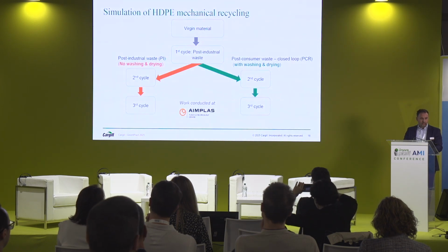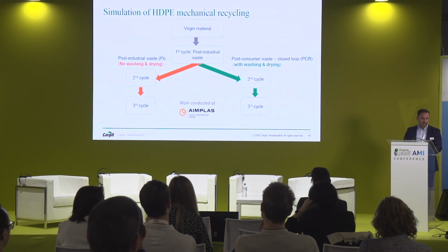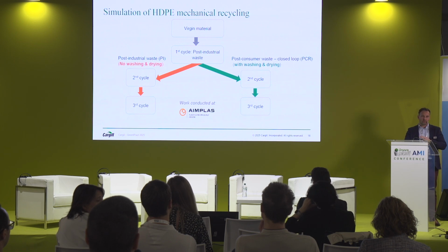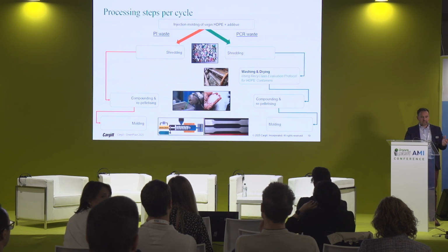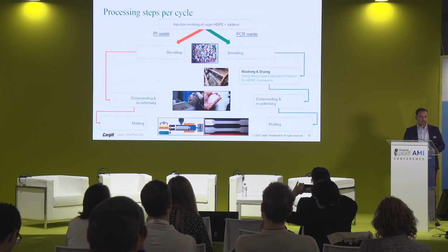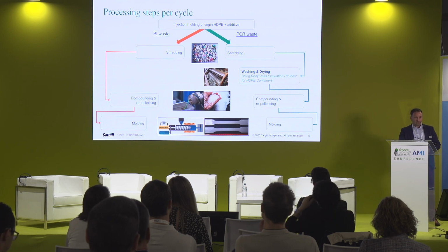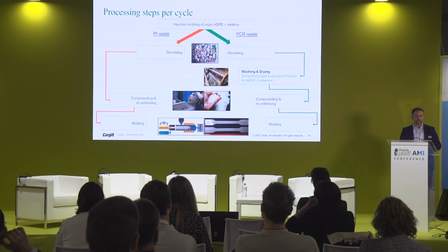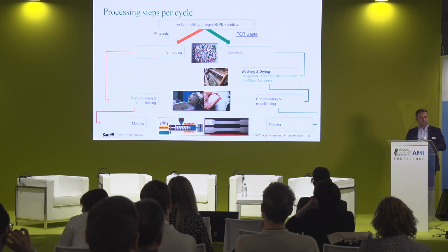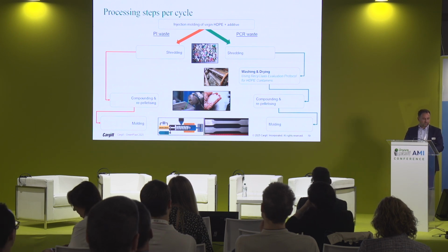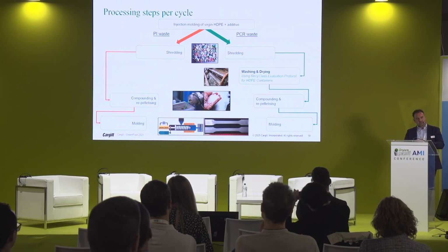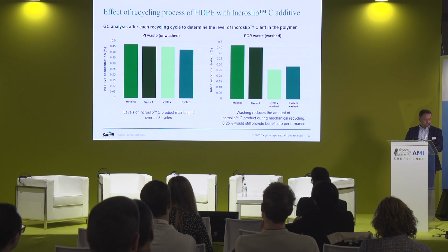We collaborated with AIMPLAS, where we sent all the materials so they can perform the study. We did two studies, one simulating post-industrial waste and one post-consumer waste. Of course, initially starting from a very clean virgin material. We used the Recyclass protocols for HDPE bottles, with very challenging conditions in terms of washing with caustic soda, 90 degrees temperature, etc. We produced specimens, shredded them, washed them, repelletized them, and repeated that 3 times.